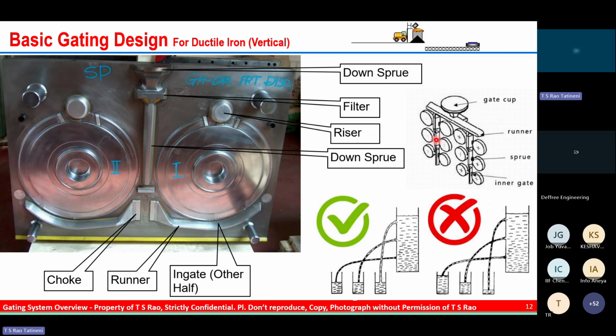In the vertical molding line, it is very important to ensure that all the cavities in the vertical environment are filled at the same time. So that is why the choke is very, very important. That plays a critical role to ensure that all three cavities in the vertical environment are filled at a time. So this is the ideal way. Suppose if the choke is the same, if the gating is the same, then obviously, because of the metallostatic pressure, the bottom cavity is likely to fill first, followed by the middle and then the top. So that is not recommended in a vertical molding line.